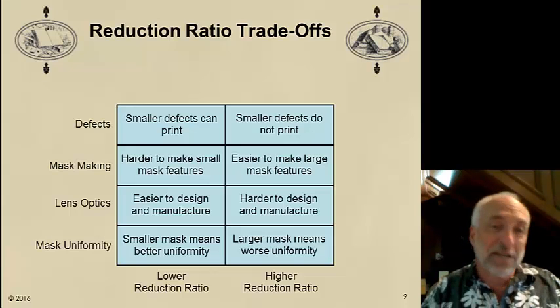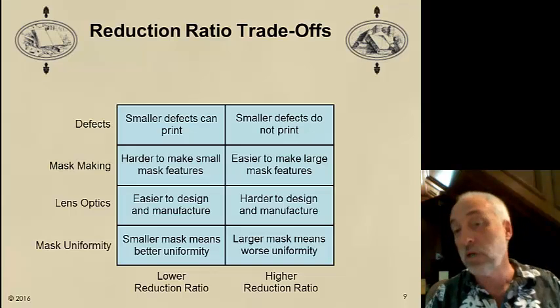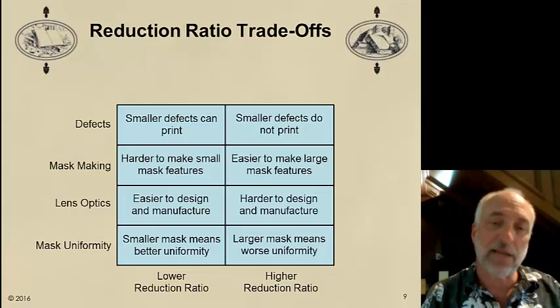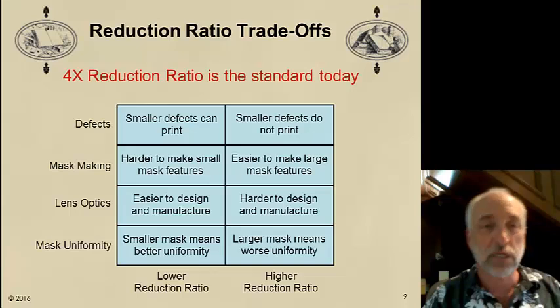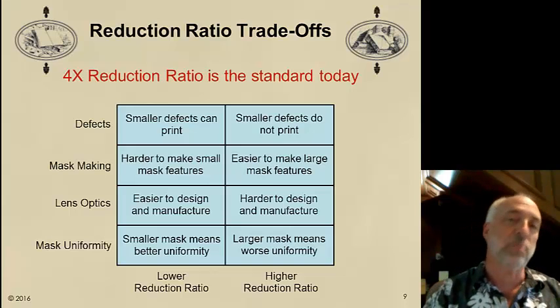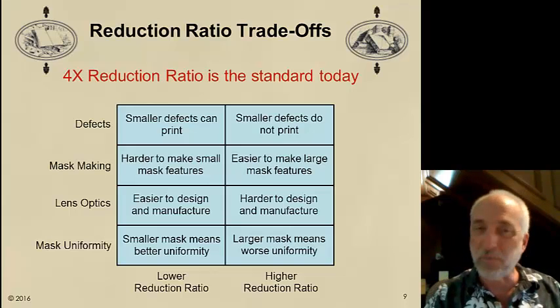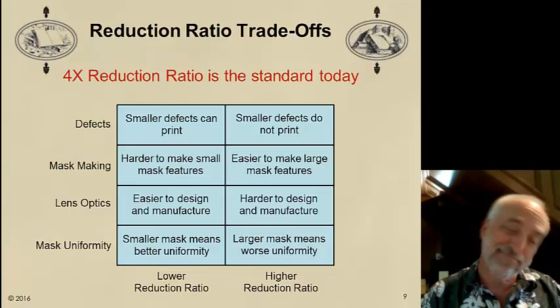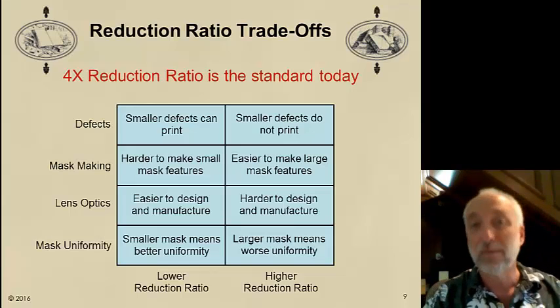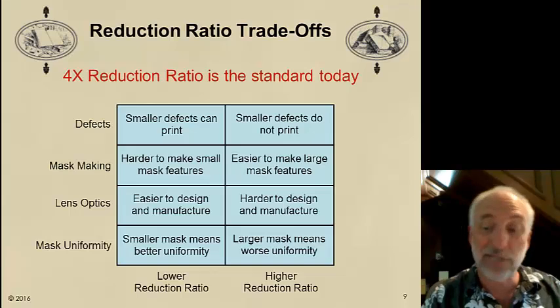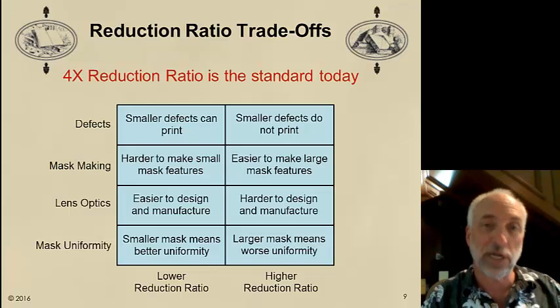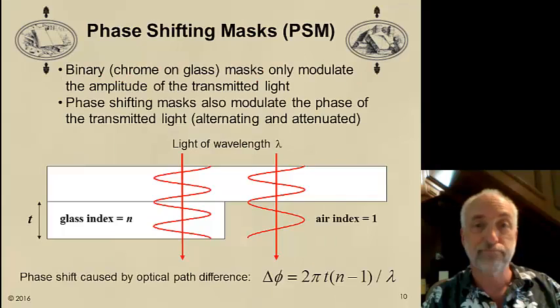So you see, we've got a couple of factors that are pushing us towards higher reduction ratios and a couple of factors pushing us towards lower reduction ratios. And the result is we've compromised at about 4x. Is this the best that it could possibly be? Well, maybe, maybe not. But it's probably good enough. It's the industry standard today, and I seriously doubt it's ever going to change, at least not in the near term.